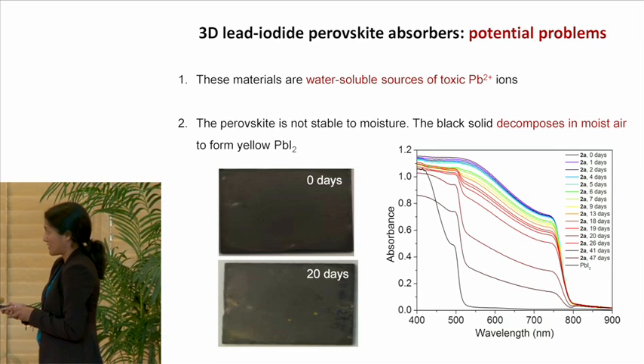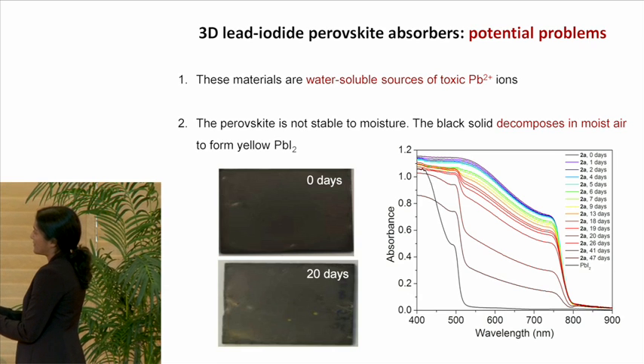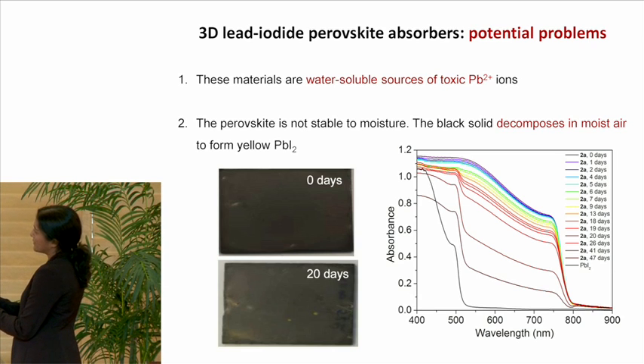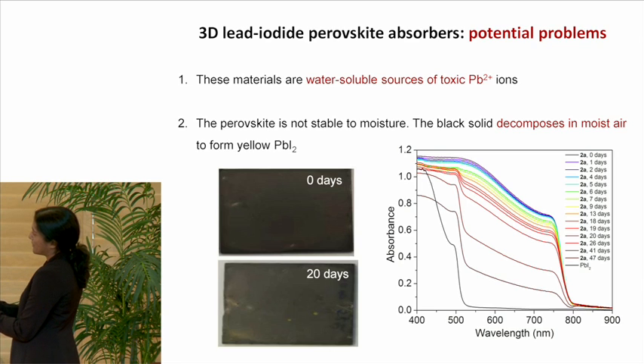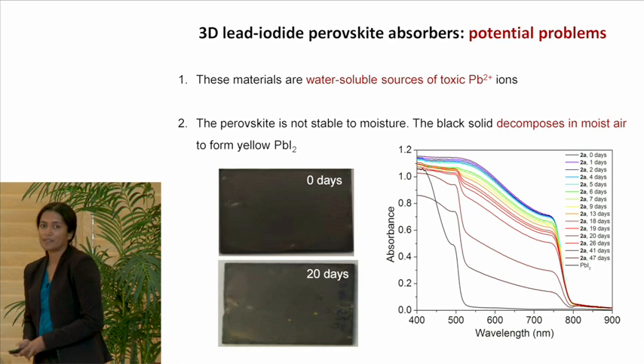In fact, you can see this even more clearly in the absorption spectrum. This is the band gap of your perovskite, and over time, you see that this band gap decreases, and there's this higher energy band gap material that forms. This shows that the perovskite material is decomposing, and lead iodide is forming instead.